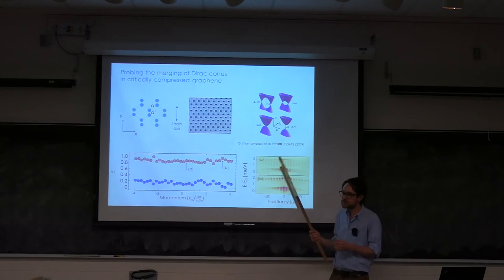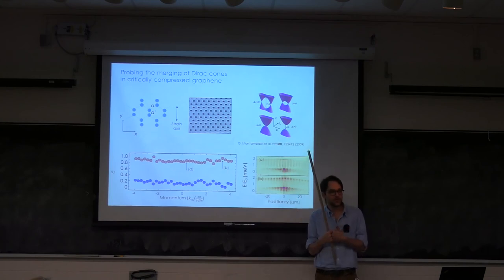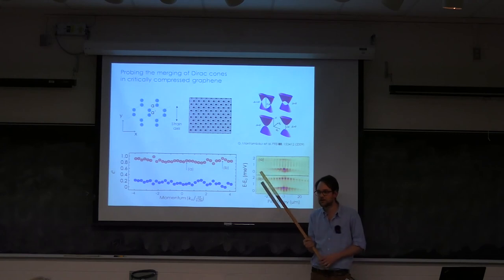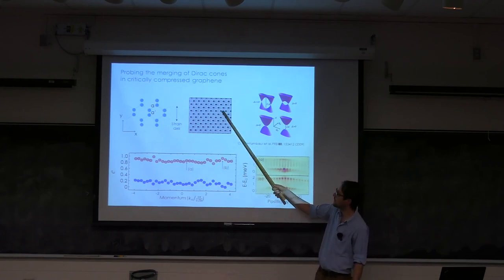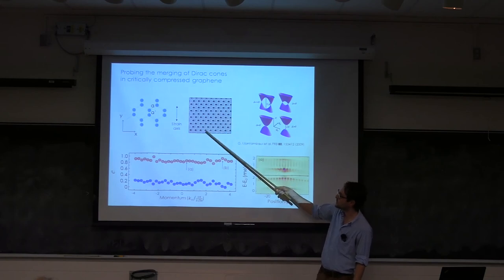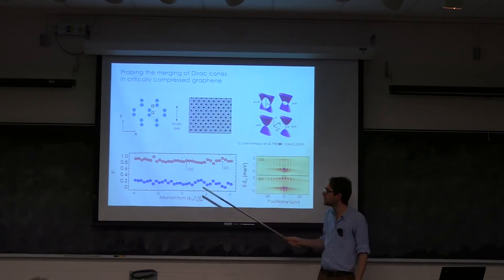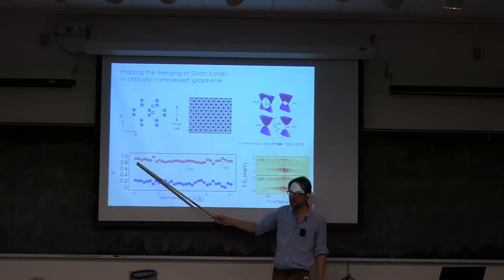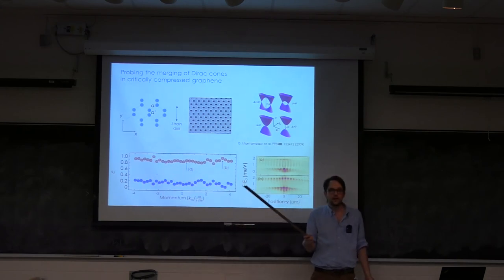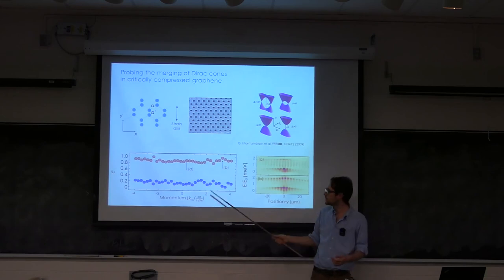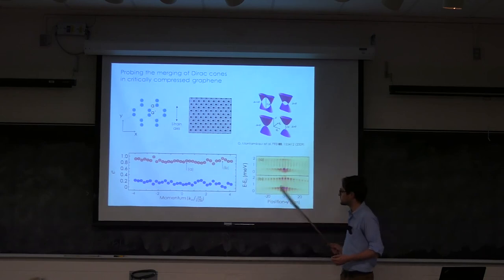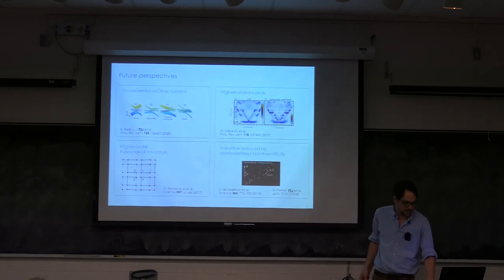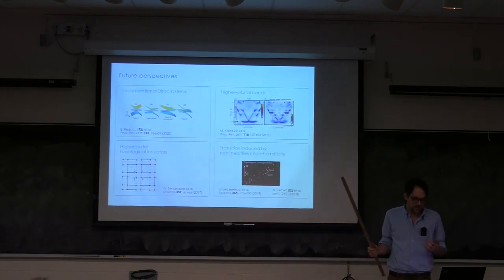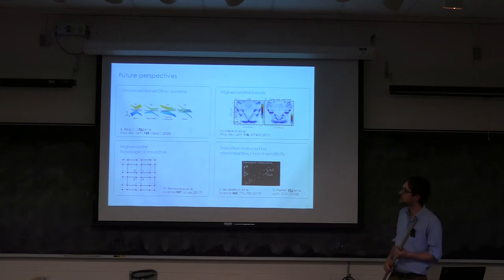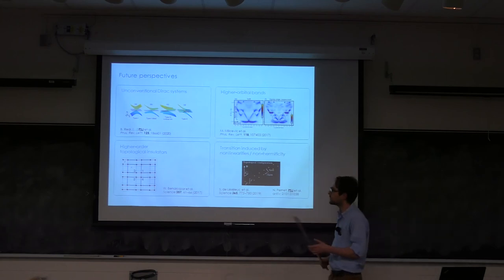Reaching this regime is impossible with graphene because it requires too much energy with respect to the chemical bonds of carbon atoms. But here we can position our atoms like we want. So this is not a distorted image. We just position the pillars like we want. And we see that now when we compute, we only have a single value. It never changes because it never crosses a Dirac cone throughout the Brillouin zone. All right, and these are different spatial profiles taken at different positions. So the perspective is that it's a really strong system to measure topological invariants in systems that have chiral symmetry. So these are interesting perspectives.